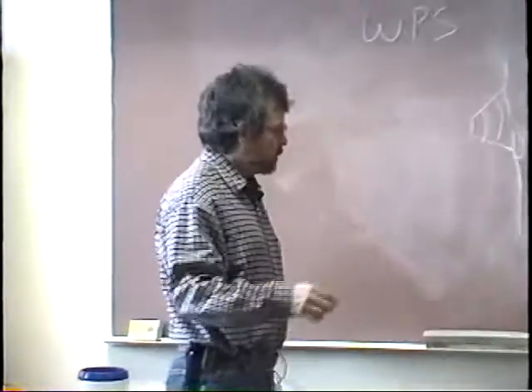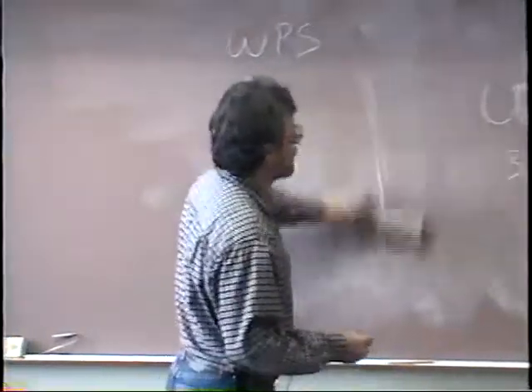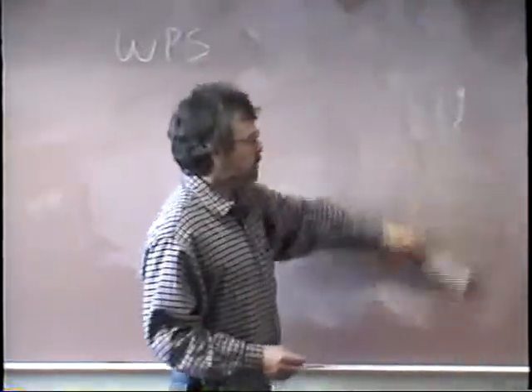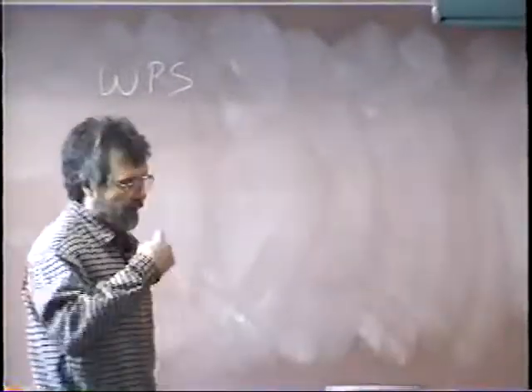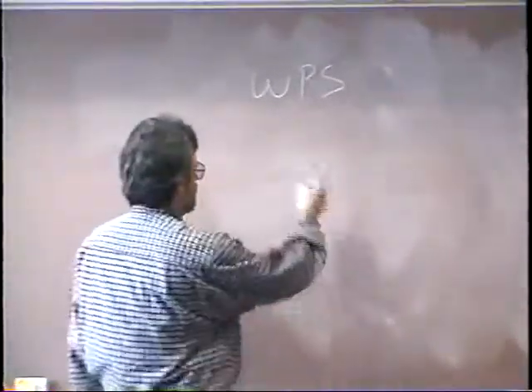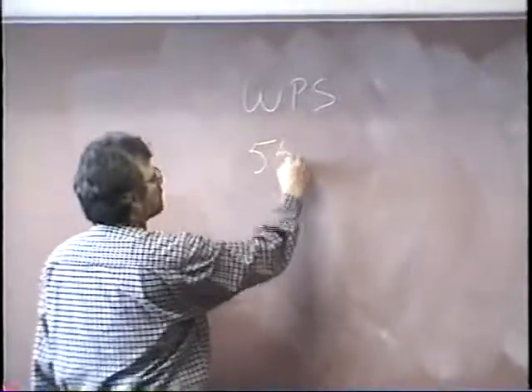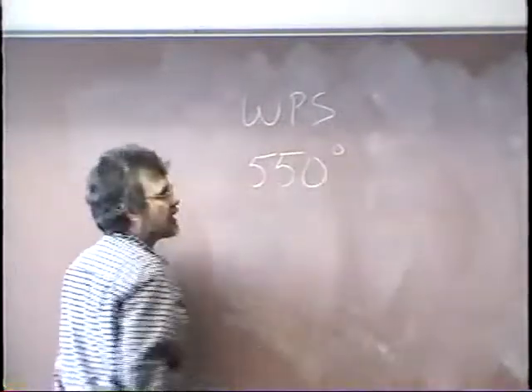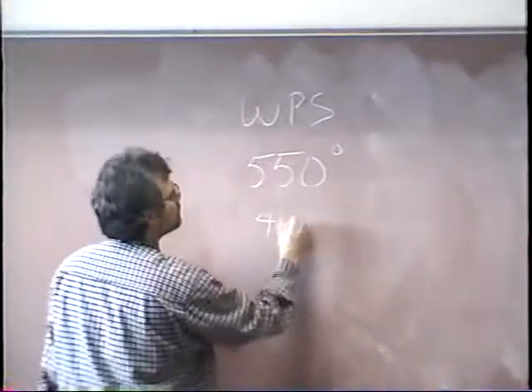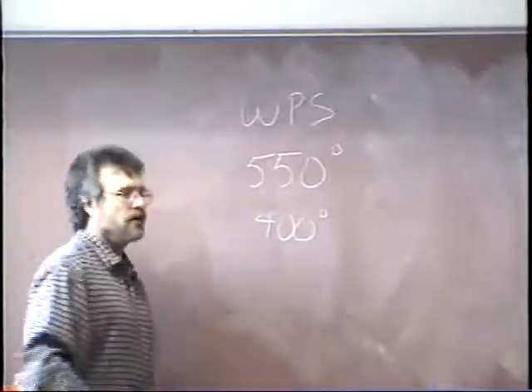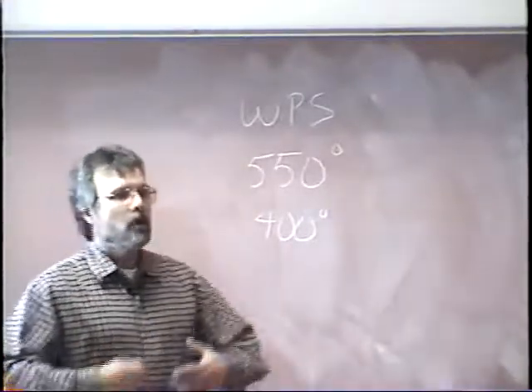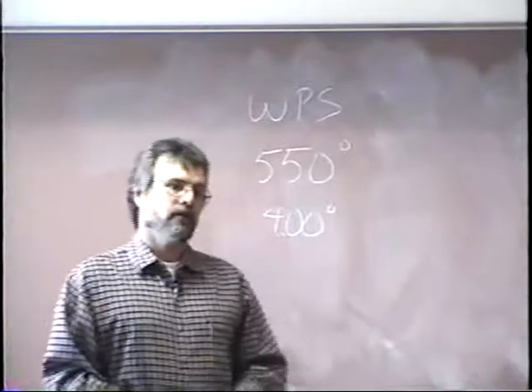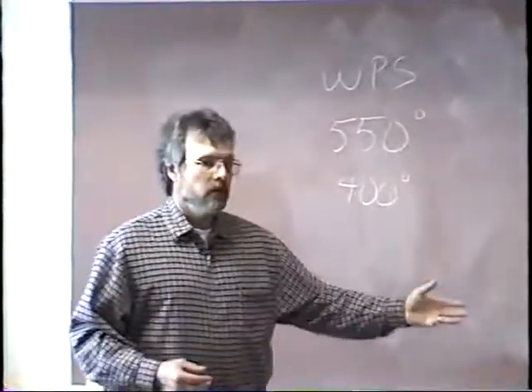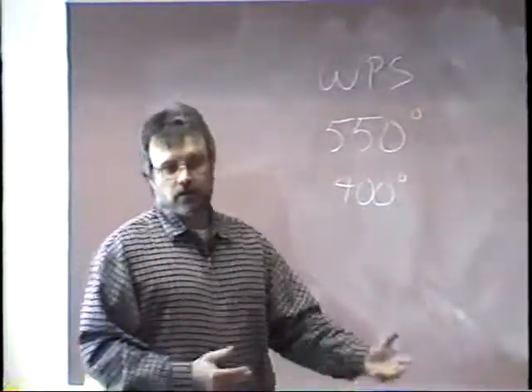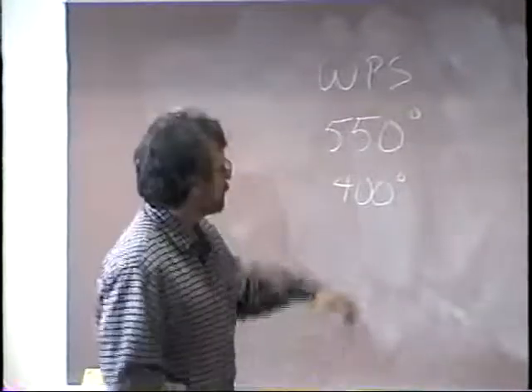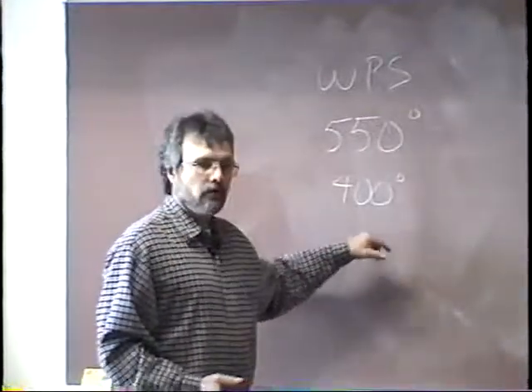So if you have a high carbon steel or an alloy steel that has a propensity for hardening and you have to preheat it, usually it'll have an interpass temperature that will say 550 maximum, and sometimes it will give you a minimum, say 400 degrees minimum interpass temperature, meaning that while it's being welded, and you've got a lot of this out at the power plant, between the shift change or lunch or whatever, the temperature of that can never drop below 400.